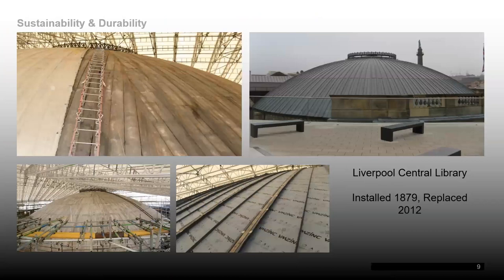Here we're looking at the Picton Reading Room, which is in Liverpool and was built in 1879 using zinc. After 133 years, many of the zinc panels needed to be replaced. However, much of the original open gap boarding was still in good condition because of the good design and installation. While the vast majority of the original design was kept, 21st century regulations meant that the panel width had to be reduced and standing seams were incorporated between the batten caps. The current corrosion rates are less than 2 microns per year, and a sheet of zinc is at least 700 microns thick.